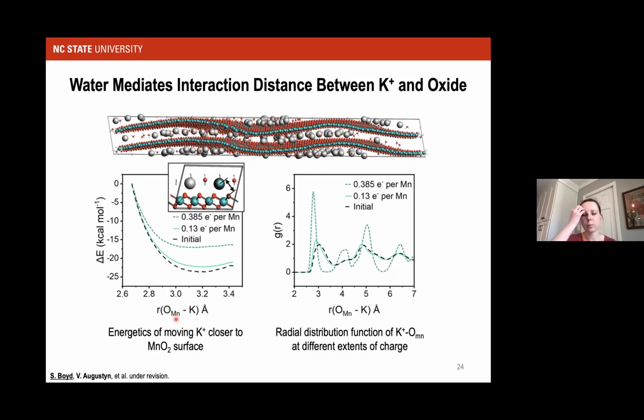We also find that the distance between the intercalating cation and the oxygen that's coordinating the manganese is essentially a descriptor of the binding distance or the interaction strength. So going back to that picture we had before of electrochemical interfaces, the distance between the electrolyte cation and your electrode surface is important. So here we find that there's a very particular preferred distance of around 2.9 or so angstroms that the potassium cations want to be from the lattice oxygens. And it's a very significant energy penalty to move them any closer to each other.